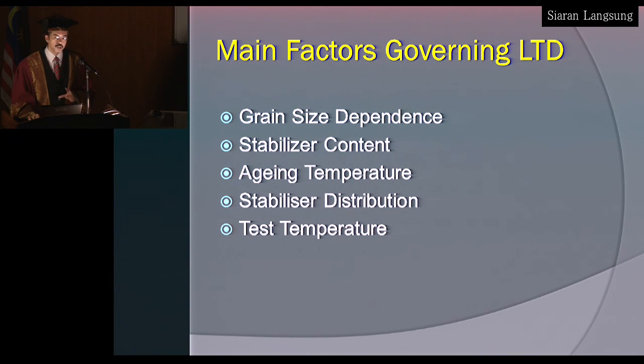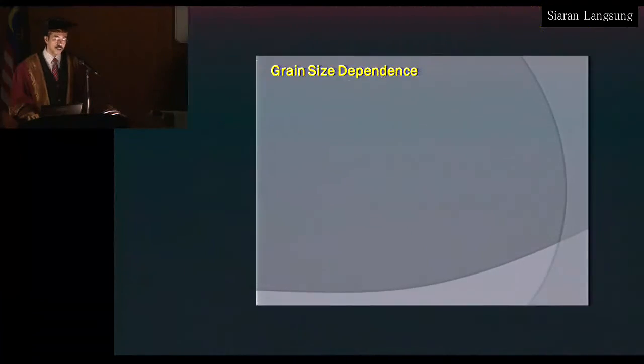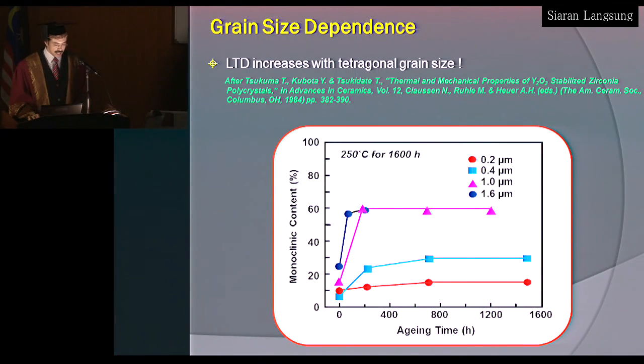So I'll quickly run through classical examples of other people's work to demonstrate how these factors control degradation. LTD increases with tetragonal grain size. As the grain size increases, so does the phase transformation. What the diagram shows is that for the blue dots, the grain size is 1.6 micron. The red dots, the bottom graph, are at 0.2 micron. Phase transformation takes place, but at a very minimum level. So as the tetragonal grain size increases, so does phase transformation.